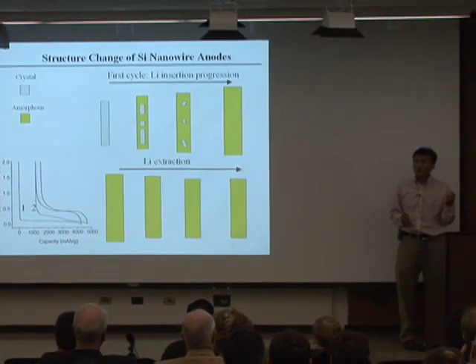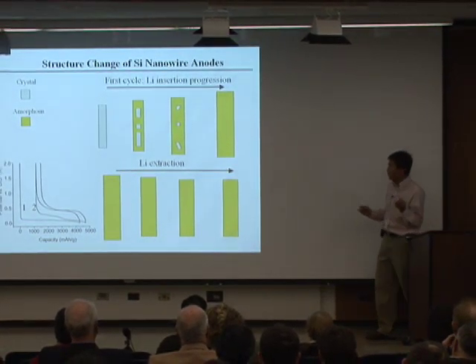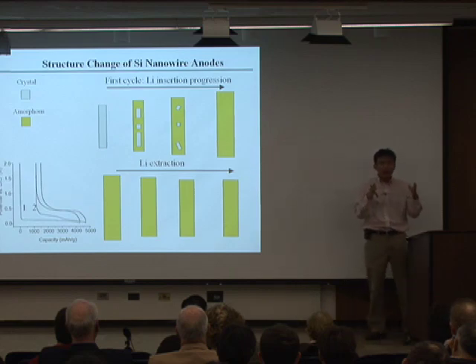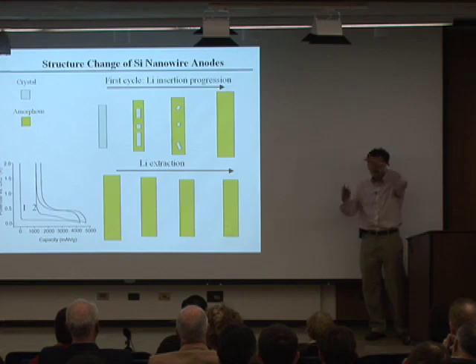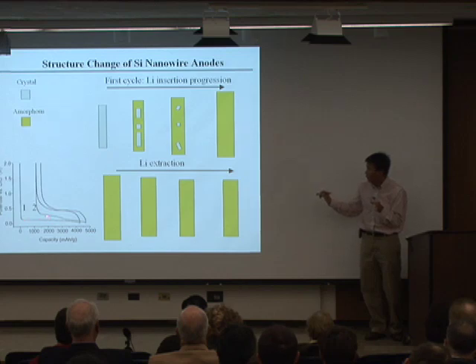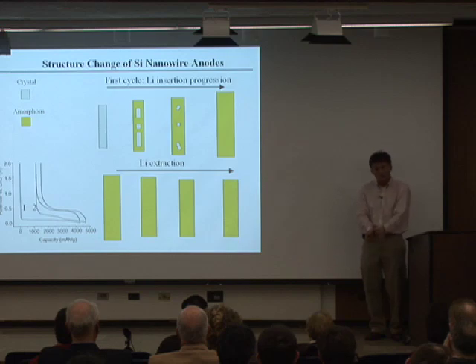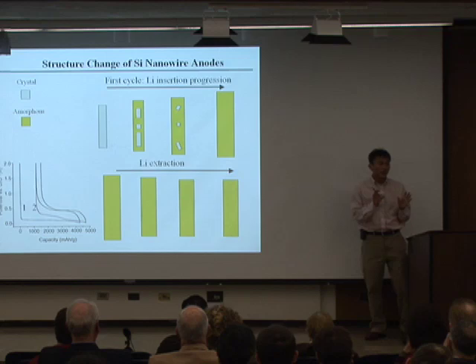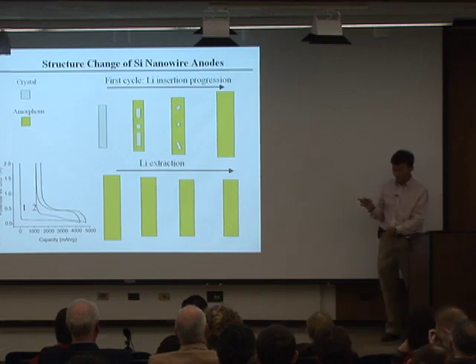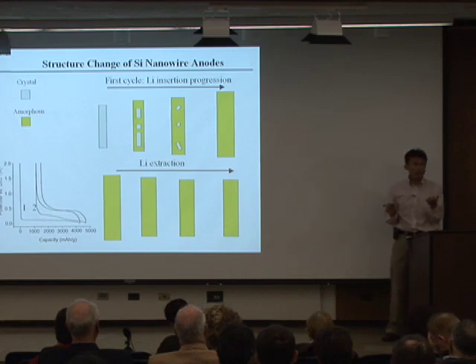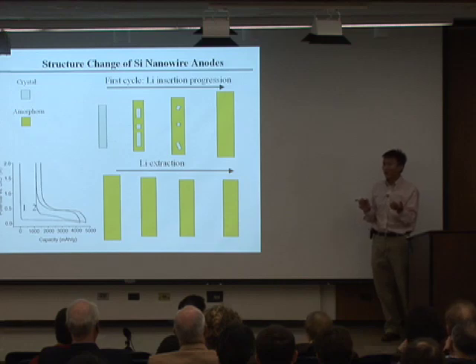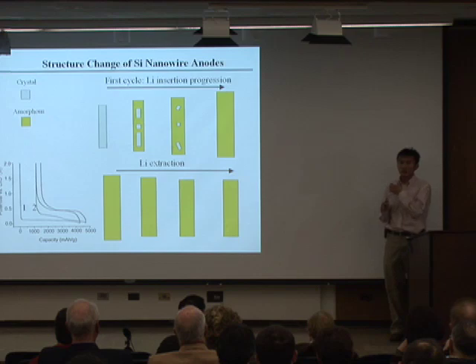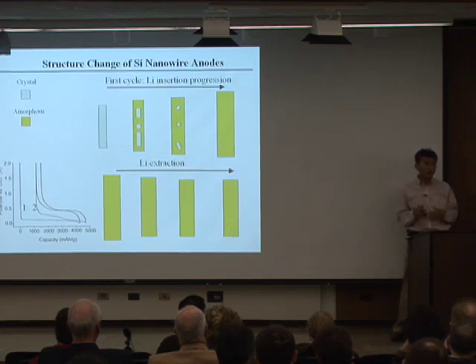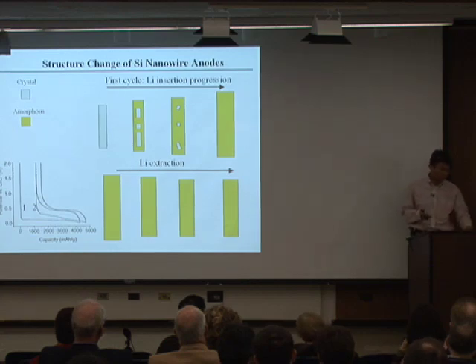We kept thinking whether it's a good idea to make a nanowire with a single crystal core and then an amorphous shell. When you charge your batteries, you only charge the amorphous phase, because you can control the voltage potential to only charge the amorphous phase, leaving the single crystal core right there without any change. So you have this single crystal core functioning as a mechanical backbone and an efficient electron transport pathway, allowing you to run many, many cycles without breaking, and to do extremely fast charging and discharging. That would be extremely important for electric vehicles, for example.